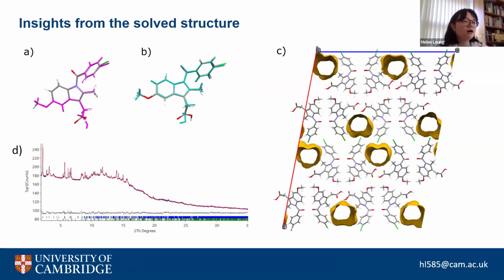But also, I want to point out C in this slide, which is these yellow circles that you might see on the slide. These represent channels that we could see. So we noticed that there was quite a lot of space in the structure. And what we realized, or the hypothesis from this direct insight from the structure, was that there had been a solvent in those channels, which was helping to template the crystallization of this specific form. And that solvent was no longer there.